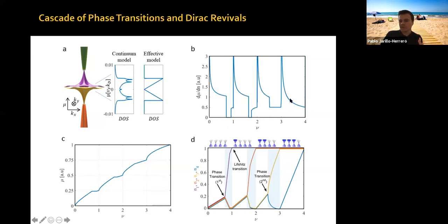Again, this looks substantially different from the experimental data, but the fact that there is a drop to zero inverse compressibility followed by a peak, which then decreases in a Dirac fashion, and then another drop, and then another peak, which decreases. The details here depend on whether this is a first order or second order phase transition, there's a Lifshitz transition or not, et cetera. But this sawtooth behavior with these asymmetric peaks, where the system chemical potential goes back to charge neutrality, is captured in a simple model where you need a critical value of interactions in order to realize this, okay? And you have also plots there of the chemical potential, et cetera.